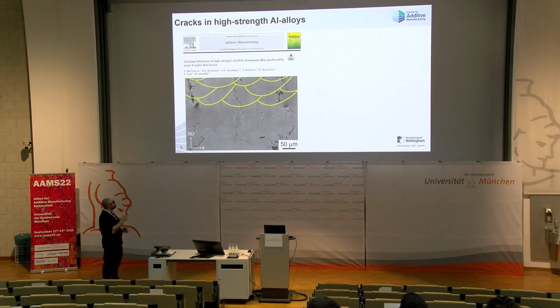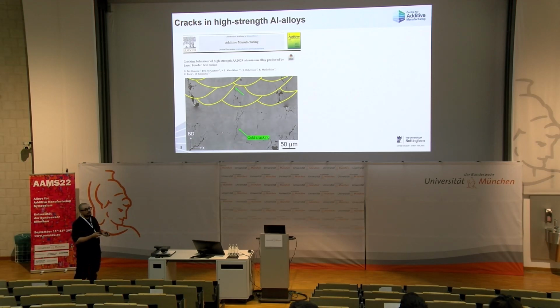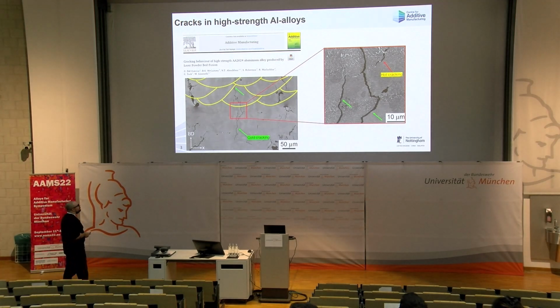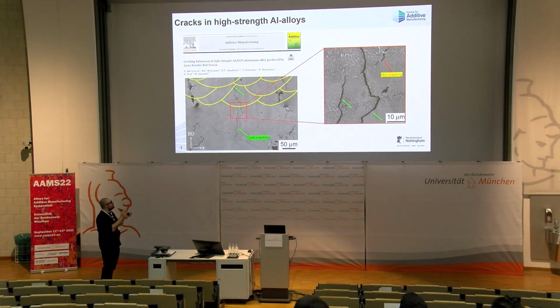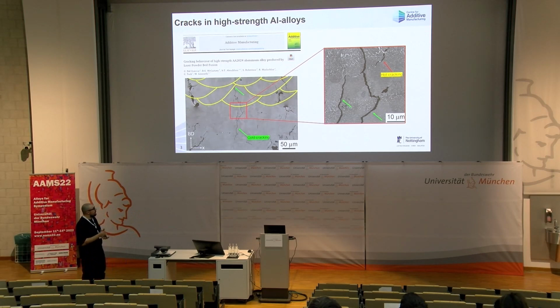And the cracks that you see here macroscopically, they are cold cracks. Cold cracks are thought to propagate from hot cracks directly. And this affects, of course, the consolidation of the build. So when we take a deep look at the microstructure here, what we can see is that apart from these macroscopic cracks that can be easily seen, there are plenty of these very, very small cracks which are randomly oriented, which are thought to be hot cracks. I selected this image because it was near a cold crack as well, but these hot cracks here can be found also in regions of the microstructure far from the cold propagated cracks.